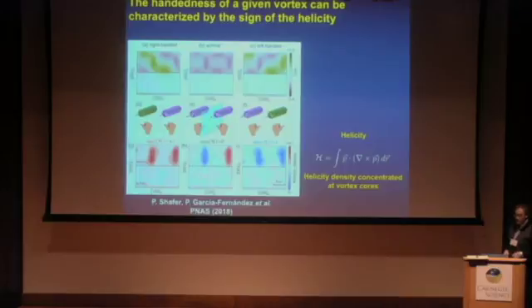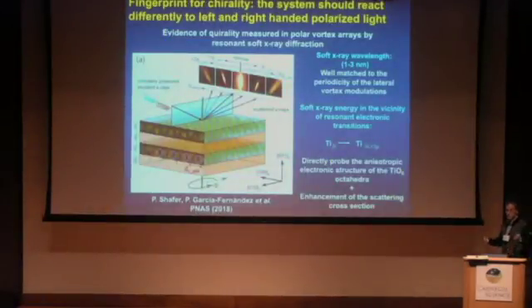So just to put some math on this, we can define the helicity. And the helicity is defined as the integral over the whole volume of the dot product of the local polarization times the curl of the polarization. Since this quantity tends to measure the rotation of the dipole, we expect that the helicity density, the integrand of this, will be localized at the position of the vortices. So just taking this equation and computing the helicity density, we can see how the right-handed structure displays a positive helicity, the left-handed displays a negative helicity, while the achiral structure has a helicity that essentially vanishes.